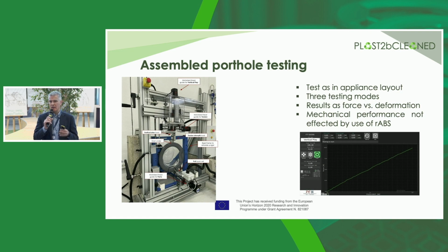Yeah, in this case, there was a testing machine which really forced the porthole in an unusual direction, in a vertical, torsional way, simulating a misuse when the porthole is closed and someone tries to push the same porthole back from the back position. The results were expressed as a displacement, deformation, versus the force applied. And again, we didn't see any change with respect to the virgin ABS. So very, very good results also in this case.